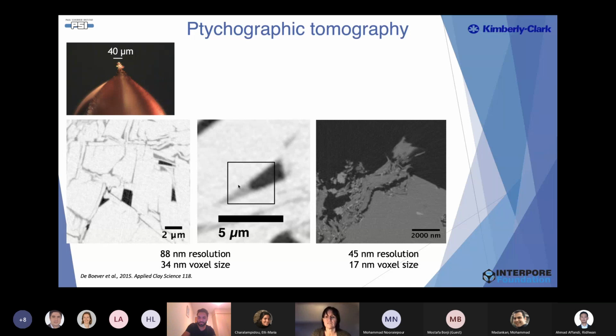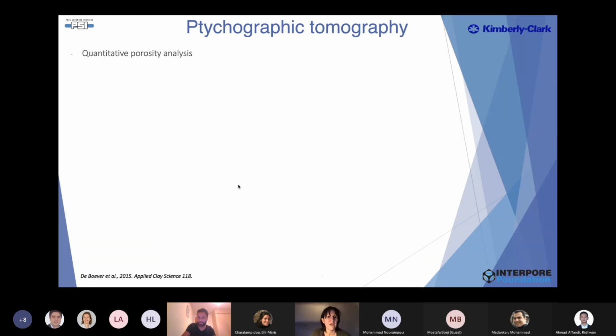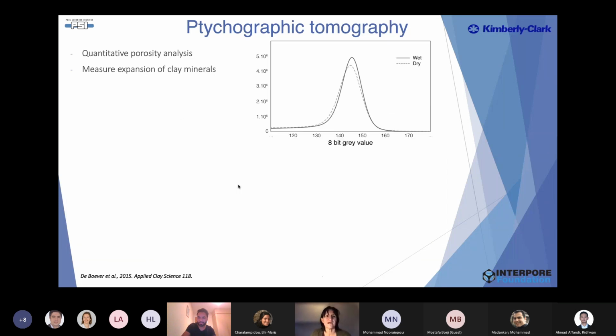We could distinguish the different materials and quantify the porosity. We can measure, for instance, the expansion of clay minerals. So if we change the relative humidity from dry to wet, you can monitor and measure this.